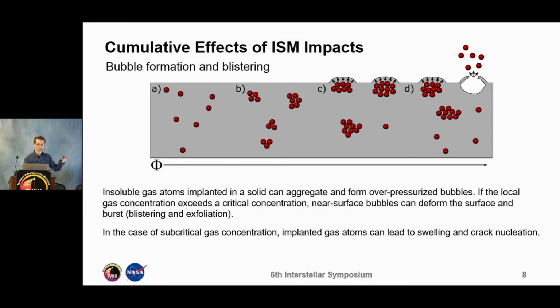Each of A, B, C, and D shows the various phenomena that can occur as a function of the fluence. At low fluences, individual gas atoms are just implanted in the material and they stay trapped in the lattice vacancies. At low fluence, about 10 to the 18 impacts per meter squared, you get nanoscale bubbles forming, but they don't aggregate and they produce no visible surface effects. In the intermediate fluence range, between 10 to the 18 and 10 to the 21 impacts per meter squared, the local gas concentration can put stresses on the material, and you will begin to see morphological changes at the surface of your spacecraft shield. And at higher fluences, greater than 10 to the 21 impacts per meter squared, the surface blisters can begin to burst, and you can get things like exfoliation, flaking, and material erosion of the surface, which is shown in D.